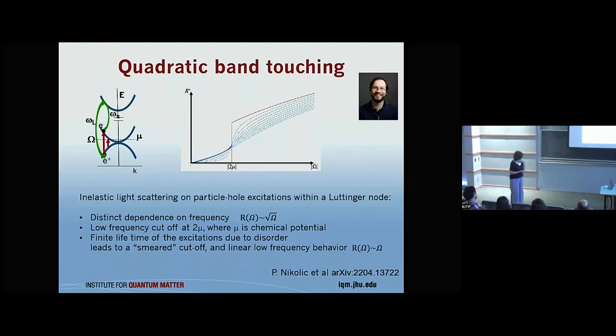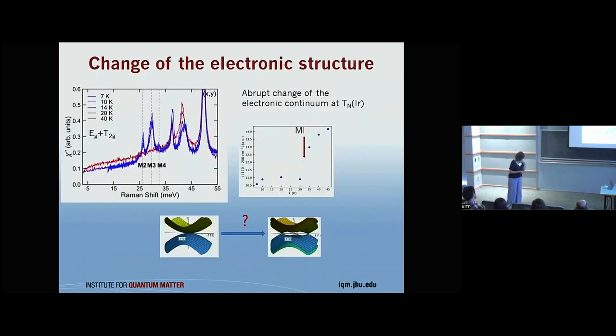And so the polarization dependence of Raman really helped us, because in the cross polarization, we completely get rid of these strong modes from the neodymium sublattice, because it's A1g symmetry. And so we observe an electronic continuum here, with some phonons and magnons on top. But the interesting part is that this electronic continuum actually changes as a step when we go from the high temperature regime into the regime where iridium moments are ordered.